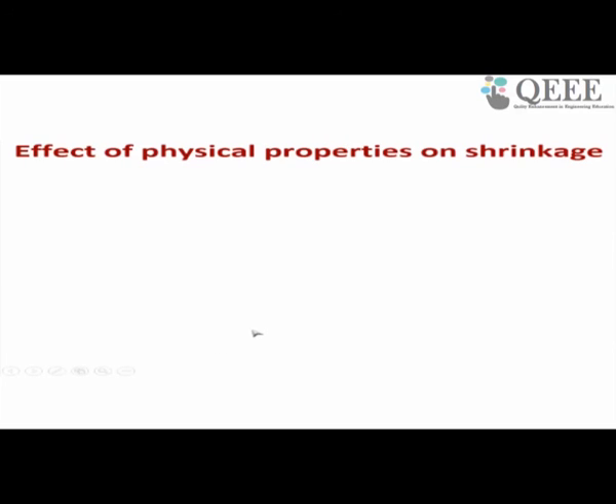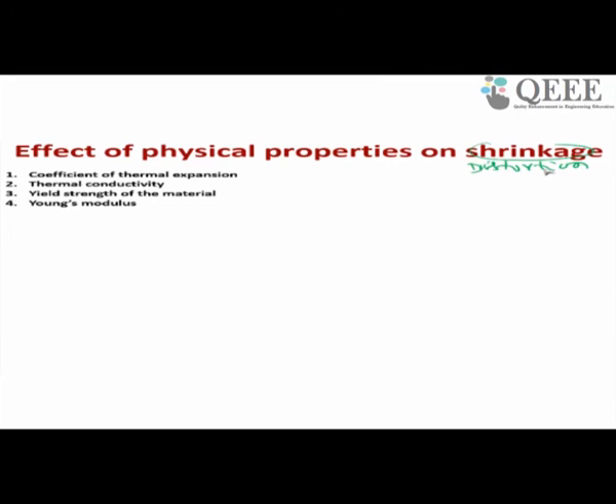Which parameters affect the distortion? This is shrinkage or distortion. The different parameters which affect the distortion are coefficient of thermal expansion, thermal conductivity, yield strength of the material, and Young's modulus. Suppose you want to join two similar materials, and the coefficient of thermal expansion is very high. What will happen to the distortion? During heating and cooling, it will expand or contract in a significant fashion. As a result, you will get very high distortion. So if a material has a high coefficient of thermal expansion, there is a high chance that it will have high distortion.